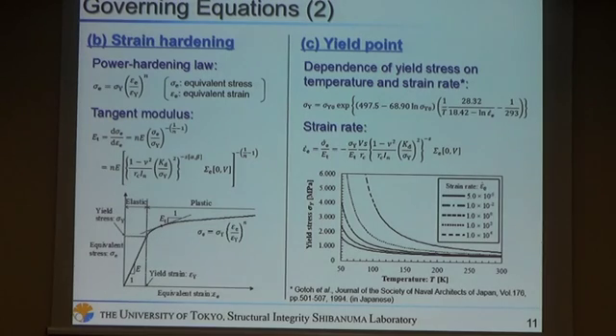The second equation is the strain hardening. We employ the general power hardening law as this equation. In the actual calculations, we use the tangent modulus form like this. The third equation is yield point. We employ the dependence of yield stress on temperature and strain rate.